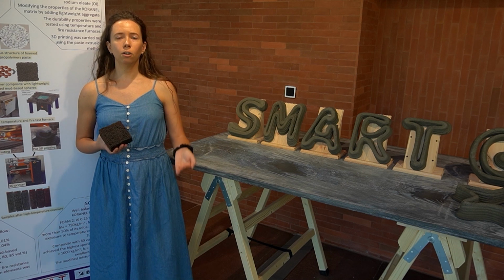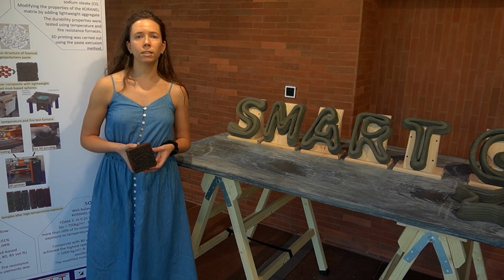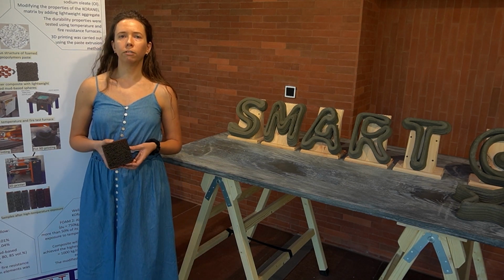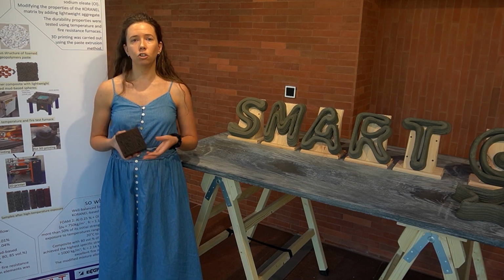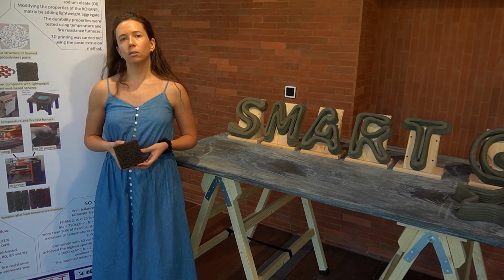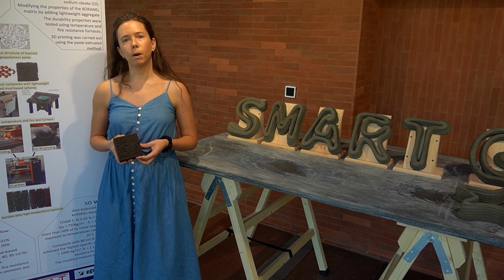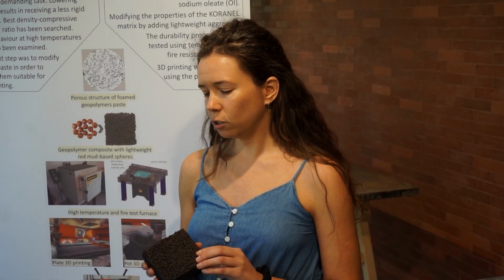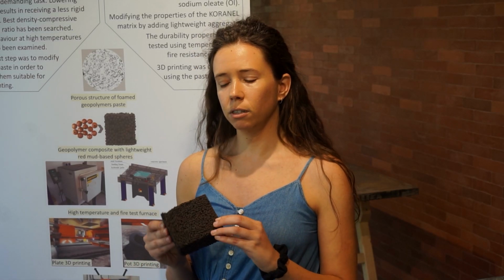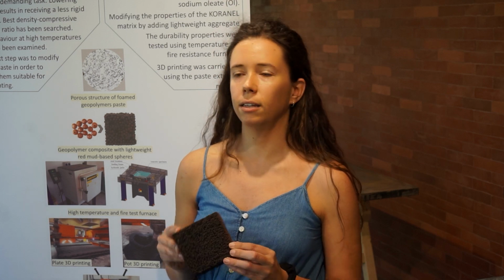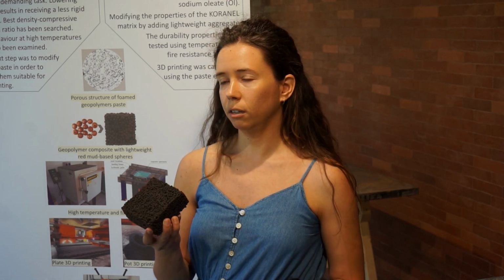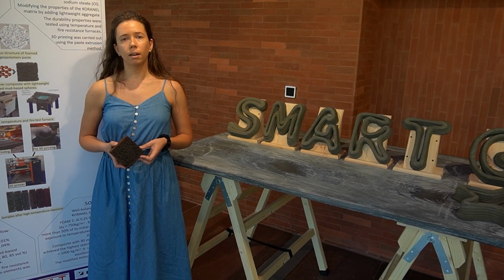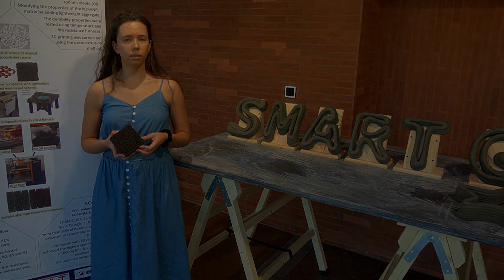But the novel route was to synthesize a new type of lightweight aggregate, in this case geopolymer spheres, that were mainly composed of bauxite residue. And with these spheres we incorporated them in the slag matrix, and we made this type of composites that demonstrate low density and also a suitable mechanical performance, high thermal stability, and also excellent fire resistant properties.